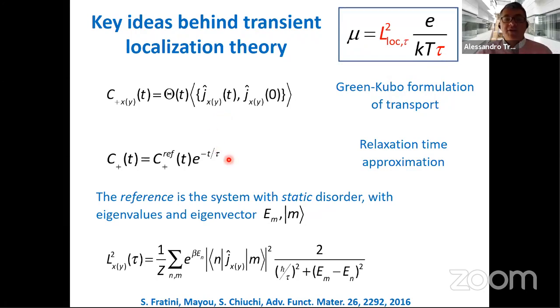So what they did was just write an approximate correlation function with the relaxation time τ, which is essentially based on the fluctuation of the transfer integral, and using the time 0 correlation function of the disordered material, essentially Anderson localization due to off-diagonal disorder. So with one parameter, which is constantly taken as 1 picosecond, you just build many disordered matrices and you plug what you find into this closed equation.